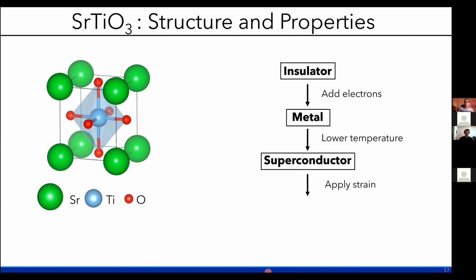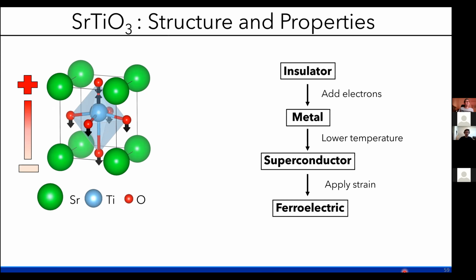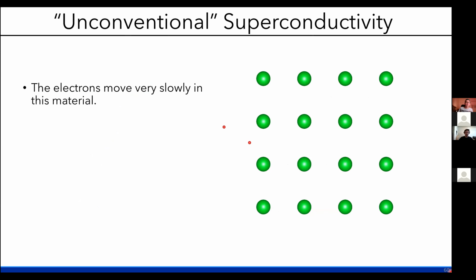So strontium titanate is an insulator, but if we add electrons to the system, it becomes a metal. And this metal becomes a superconductor at low temperatures. And furthermore, if we apply strain to the material, we can achieve a ferroelectric state where the titanium ion has shifted up and the oxygen anions have shifted down. And this results in a polarization, since the positive charges have shifted up and the negative have shifted down. And so we get an electric field generated in the ferroelectric state. And so aside from the fact that strontium titanate can exist in all those states that I just described, we're mainly interested in this material because the superconducting state is really unusual.